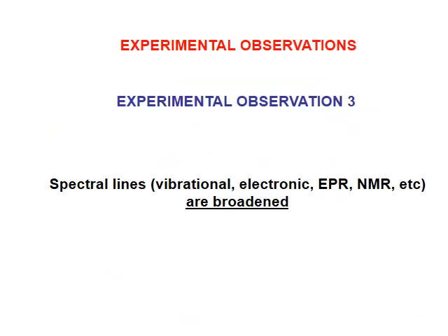There is a third experimental observation, from some experimental techniques we must say, that may be used in the characterization of what we call a glass. These are spectroscopic techniques. Glasses are amorphous, and for that, a distribution of bond distances and angles is expected. Any spectroscopic technique sensing bond distances and angles will display broadened lines.